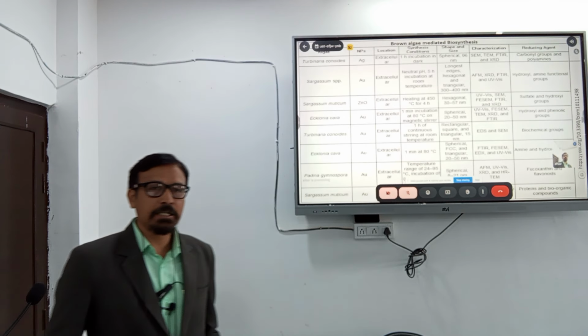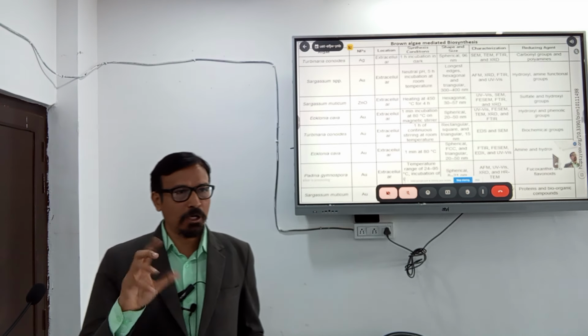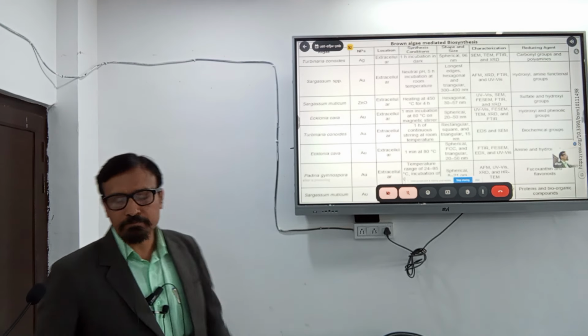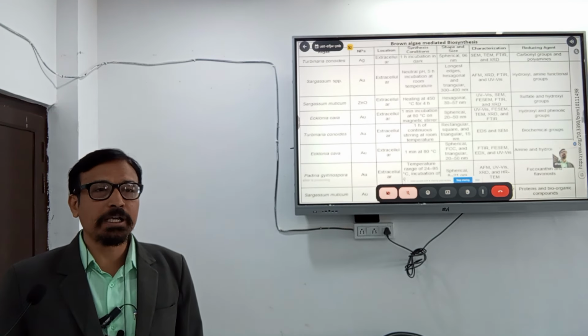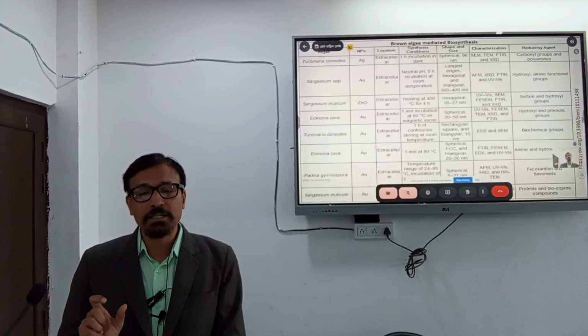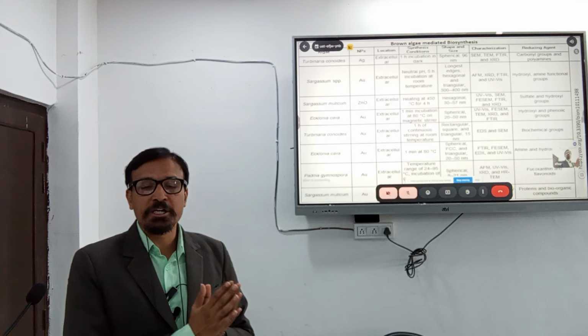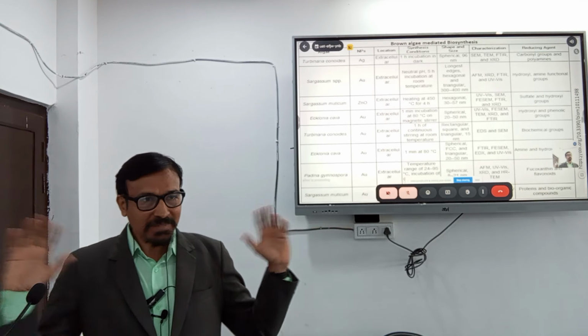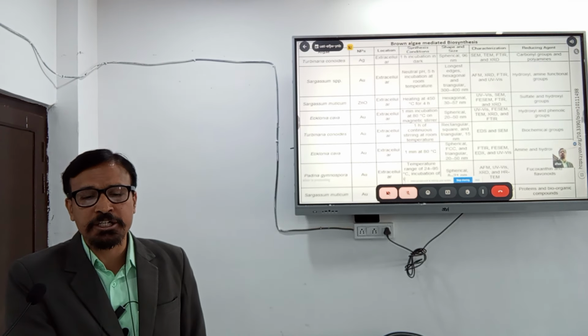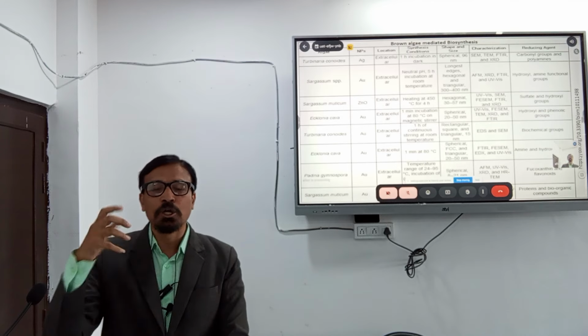So there are many ways to synthesize nanoparticles with algae, that is phycosynthesis, brown algae mediated biosynthesis. These are the algae with which we can synthesize the nanoparticles. First, Turbinaria conoides can produce silver nanoparticles, and the synthesis condition is 1 hour incubation in the dark. So we have to create dark conditions for the synthesis of nanoparticles with this particular algae, and the spherical size of those nanoparticles will be 96 nanometers.